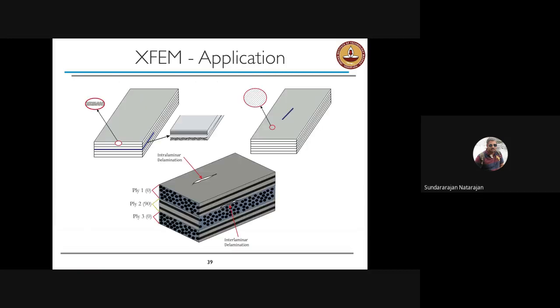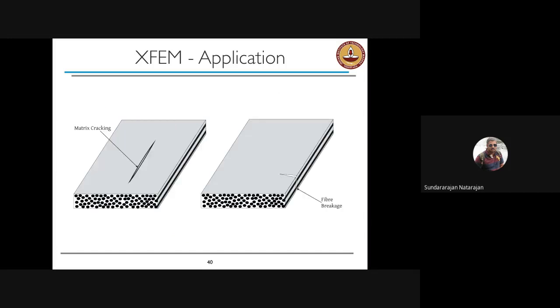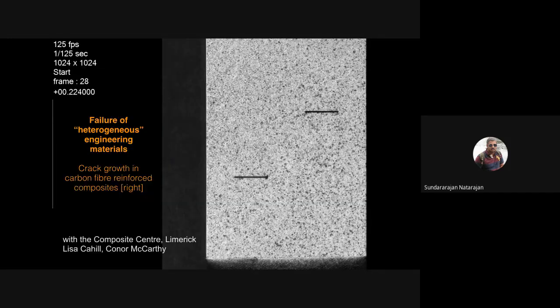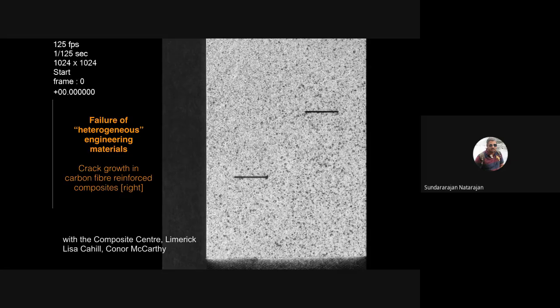So we have also applied XFEM to look at fracture in laminated composites. So laminated composites have typically two distinct fracture behaviors. One is interlaminar delamination, or fiber breakage, right? Or matrix cracking or fiber breakage. So this is an experimental video where you have a composite plate. It's a laminated plate, and you have two slots. The solid black lines that you see on the image are the cracks, and then this is subjected to far-field tension.